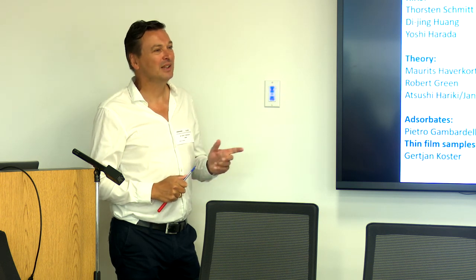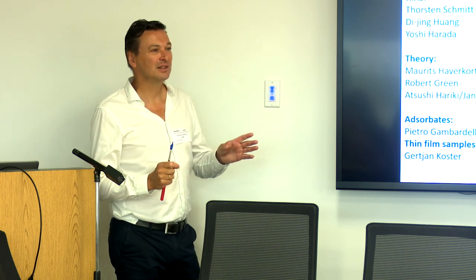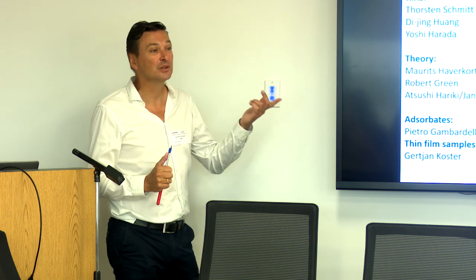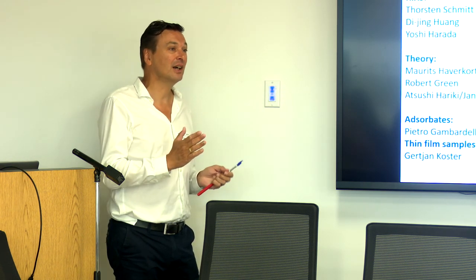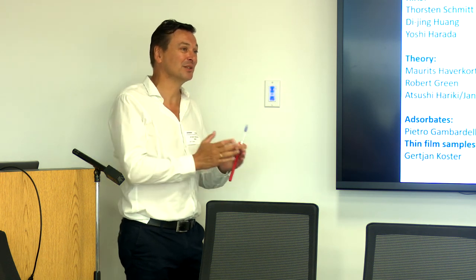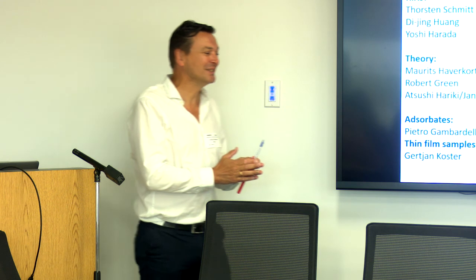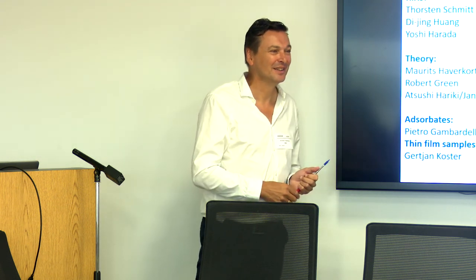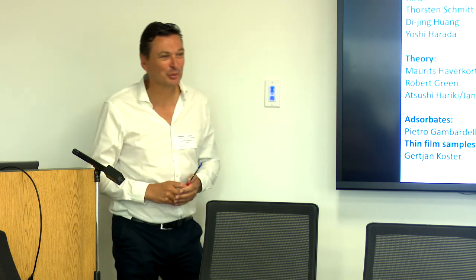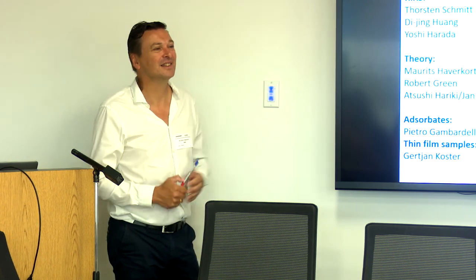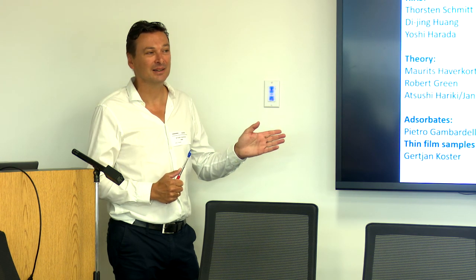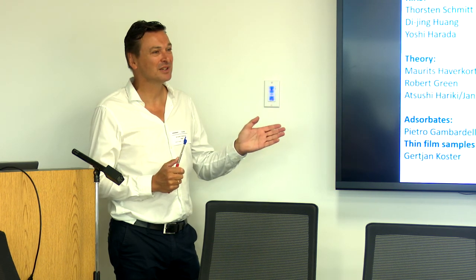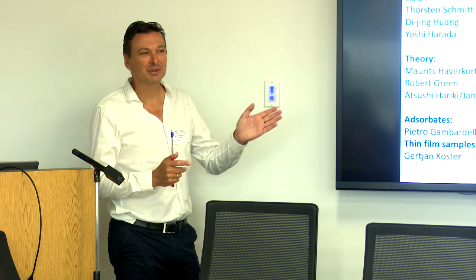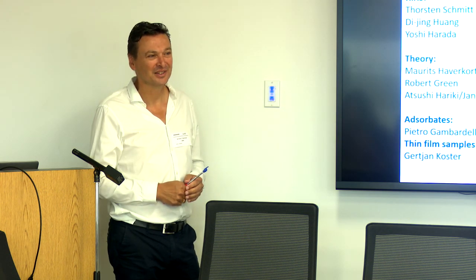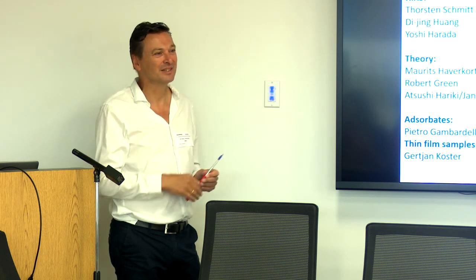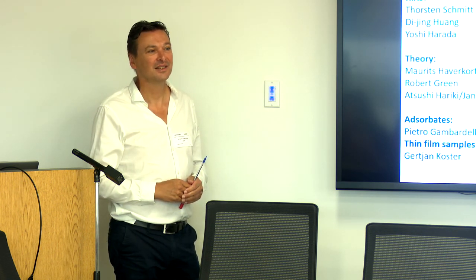Yeah. So probably many simple oxides like nickel oxide are exactly very close to the normal ratio. So I think that there are oxides where it's a normal ratio and there are oxides where it's a non-normal ratio. And the non-normal ratio oxides might be very interesting from a color point of view, which is the important thing in ruby, but also in luminescence. And so this is my prediction, that for luminescent systems you would probably be far away from the normal ratio. Octahedral oxides will be fine. I get your logic, that's interesting. Yeah.